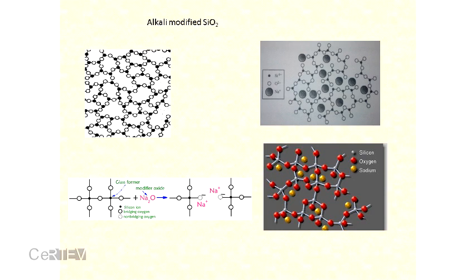You can understand that chemically, when you add sodium ions or lithium ions, we can break one bond and form a bond like this. So this oxygen has an extra electron, and that bond is satisfied, neutralized with the addition of sodium ions. So the alkali ion is forming a so-called ionic bond that is loosely bound, and there are non-bridging oxygens. So by introducing alkali ions in the silicate network, we have non-bridging oxygen. You can see the oxygen ions ending, forming no other bonds on other sides. But here oxygens are forming bonds on two sides. So there are non-bridging oxygen ions and alkali ions. These are the structural models which we consider for conduction hopping. This is the molecular simulated result.